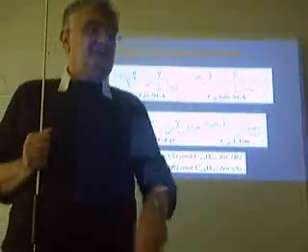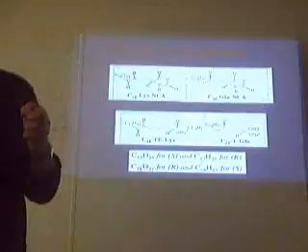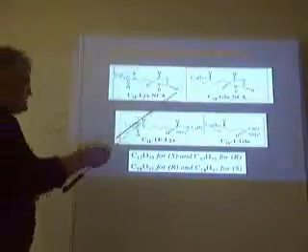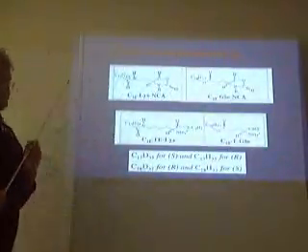If it takes place along a glide plane, you define a mirror, and therefore this glutamic acid N-carboxyanhydride crystallize in an achiral space group, not centrosymmetric, because you cannot have a center of symmetry, but along a glide. That is the problem. So first of all, we had this idea: let us try to generate the system, and we shall see the problem that Gunther just laid out.